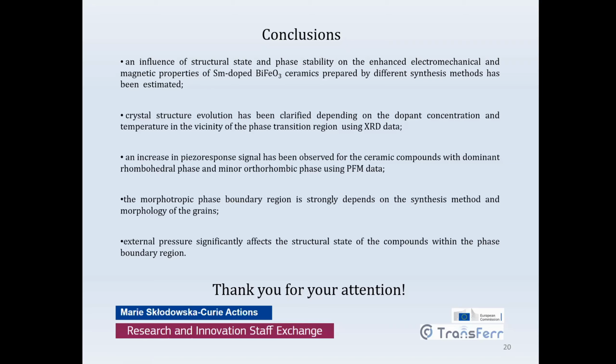So the idea was to find the way, using chemical doping, to release remnant magnetization, to have two active ferroic orders, to have magnetization regardless of its origin. The ideal case is to have ferromagnetism, because the initial compound is antiferromagnetic. And simultaneously we have to keep polar order, to keep the compound ferroelectric. So to play between these orders and get magnetoelectric coupling.